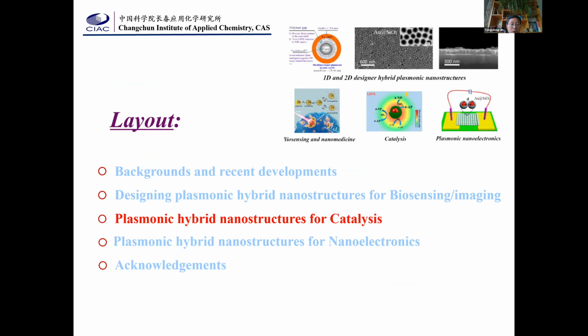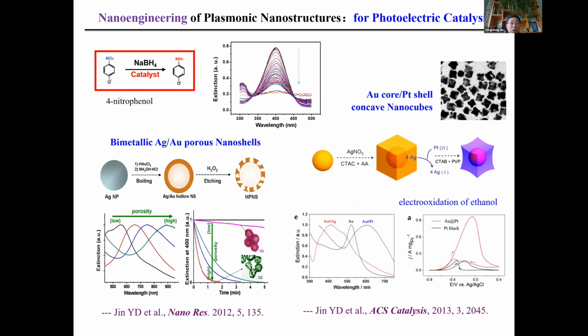Next, I will briefly introduce our work on plasmonic hybrid nanostructures for catalysis. We are interested in nanoengineering of plasmonic nanoparticles for photocatalytic applications. For example, we developed an all-solution route to prepare silver-gold porous nanoshell by tuning the porosity of the particle. The catalytic activity in the case of 4-nitrophenol reduction to aminophenol can be well tuned. Also, we prepared gold core platinum shell concave nanocubes. It shows much better electro-oxidation of ethanol than commercial platinum black.